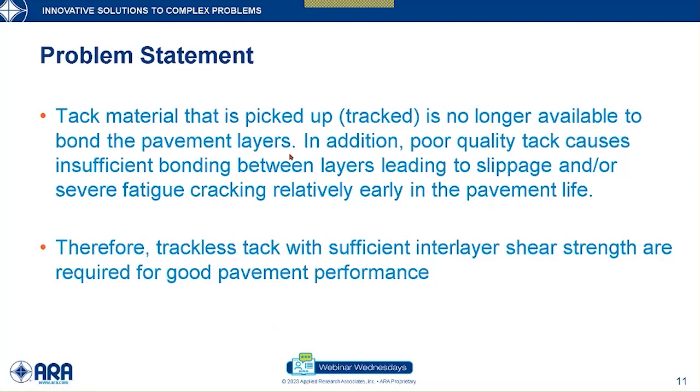Okay, so based on the discussion of the tracking and bonding issue, the problem statement of this research would be: the tack material that's picked up by the construction vehicle tires is no longer available to bond your pavement layers. So this poor quality tack can cause insufficient bonding that can lead to slippage failure and ultimately fatigue cracking. And that can occur very early in your pavement life if there is not enough tack coat between the layers of your pavement.